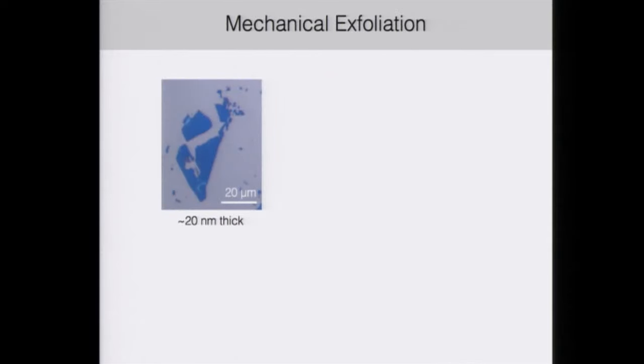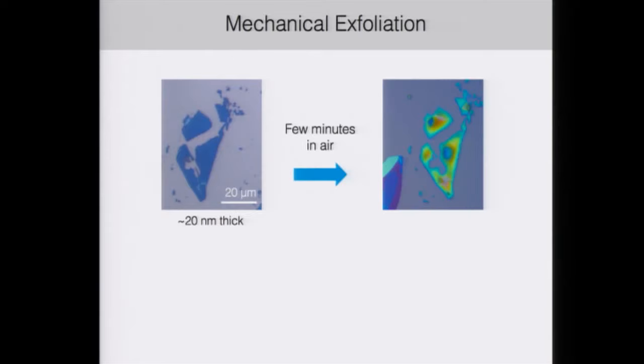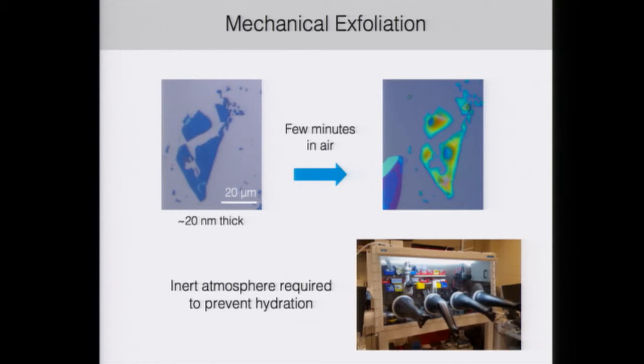So we can mechanically exfoliate by cleaving the crystals thinner and thinner using Scotch tape, and then place them onto a silicon oxide silicon substrate. And so in this manner, we're able to obtain fairly thin crystals. However, unlike graphene and other air-stable materials, after just a few minutes in air, these crystals will rapidly hydrate and absorb water and eventually dissolve into puddles. So we quickly learned that an inert atmosphere is required to prevent hydration.